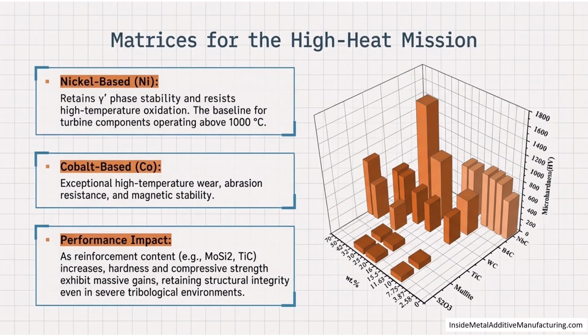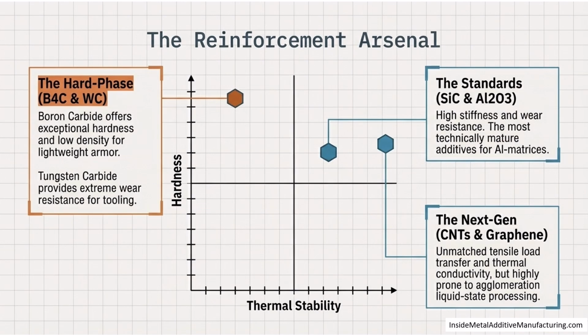In the high-heat regime, nickel remains the gold standard for turbine components because of that crucial gamma prime stability. However, cobalt matrices are emerging for severe tribological environments due to their superior wear and abrasion resistance. As you can see from the 3D plot, as we increase the weight percentage of reinforcements like molybdenum disilicide or titanium carbide, we see massive gains in micro-hardness, allowing these components to retain structural integrity even in the most severe abrasive environments. Our reinforcement arsenal is divided by performance.